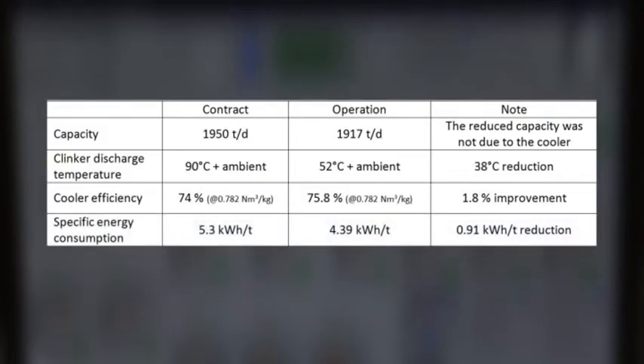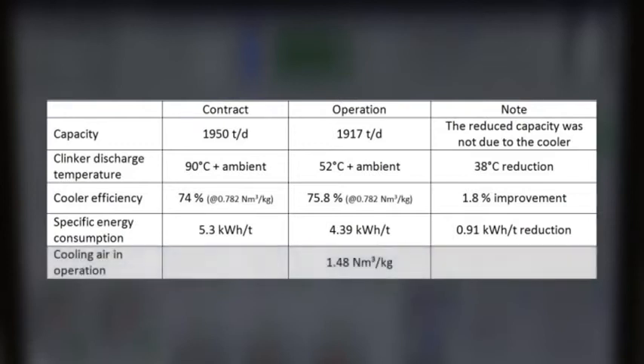The specific energy consumption is only 4.39 kilowatt-hours per ton. The specific air consumption is below 1.5 norm cubic meters per kilogram. On top of that, a reduction of 2 to 3 kilowatt-hours per ton on cement grinding could be marked due to the improved clinker quality.